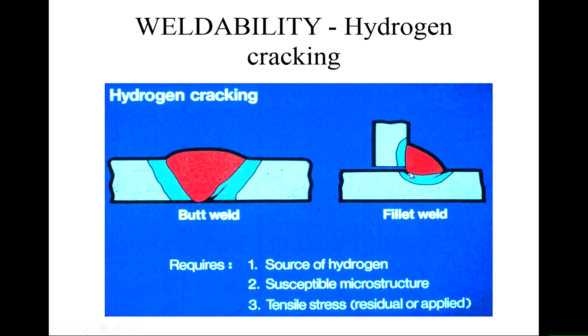And there's another one here where there's a change in cross-section, so there's stress concentration. The toe of the weld here has more defects in it than the bulk of the weld, and that's why that tends to be a starting point. In a butt weld, again near the penetration bead, this is a case here where we got lack of penetration on one side, so again you can get the crack coming in there.